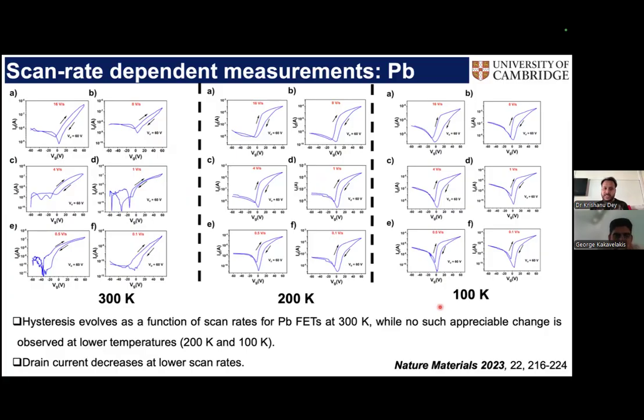So that tells you that this change in hysteresis has got to do something with temperature, and hence also with the motion of ions. And another way of understanding that is that the drain current that you see at higher scan rate reduces quite significantly as you go down to lower scan rates, and that's also because of some ionic screening. So if you give more time for the ions to move, they can screen better, and you will get lower and lower drain current. So both of these things show you that in the lead-based perovskites, the transport is very much affected by the ions.